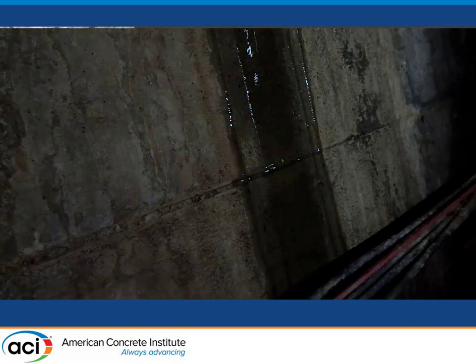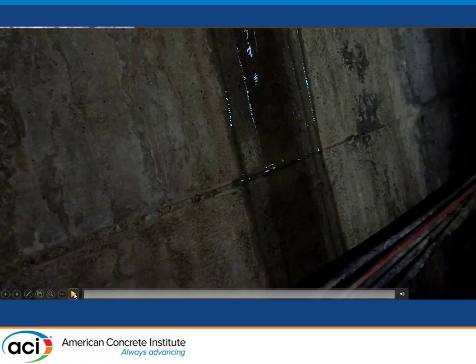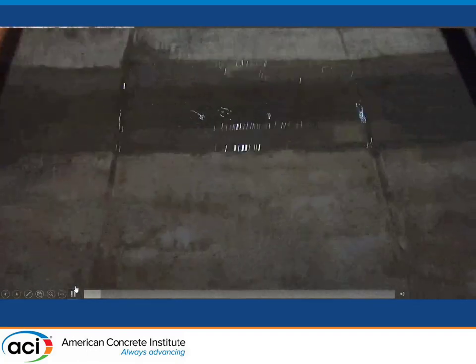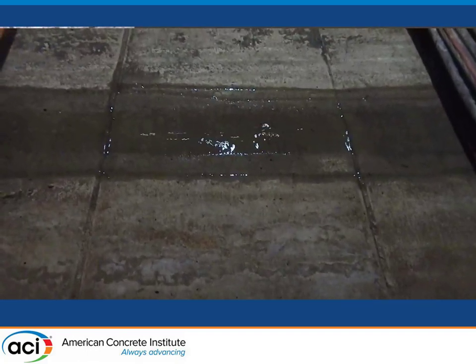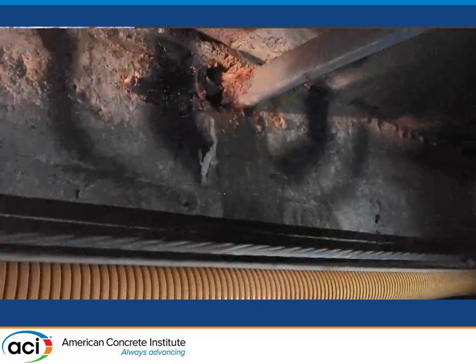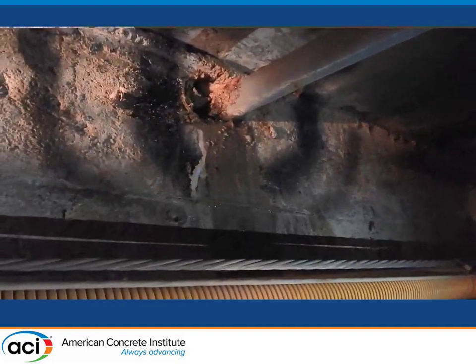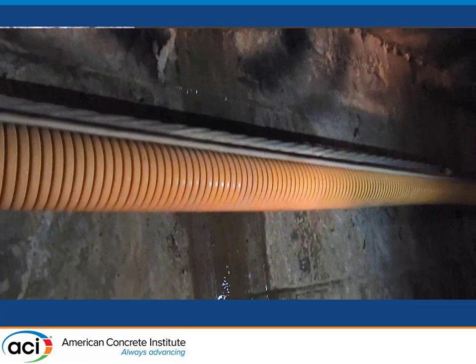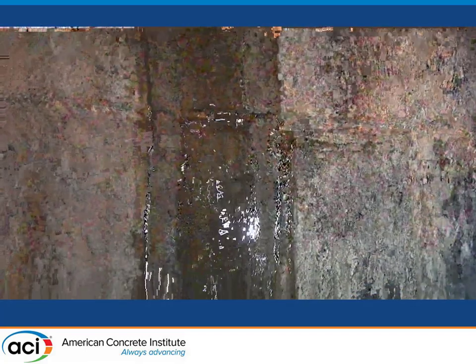Also along the walls — and this is one of the things we think was a precursor for the external sulfate attack problems — on that day we walked in and there were basically waterfalls of water coming in through every single nook and cranny along the tunnel structure. We ended up with an accumulation of approximately four inches of water at the bottom of the structure — it was really just pouring in.